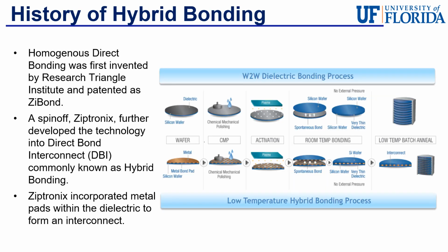The first form of hybrid bonding actually had nothing to do with a hybrid bond, but was instead a technique called homogeneous direct bonding, and it was first invented by the Research Triangle Institute and patented as ZiBond. Now, homogeneous direct bonding was a process where a very thin dielectric was formed on the surface of a wafer, polished smooth, and then activated via plasma to become hydrophilic, so that when the two wafers were brought together at room temperature, they would form a spontaneous bond through a process called hydrophilic oxide-to-oxide bonding.